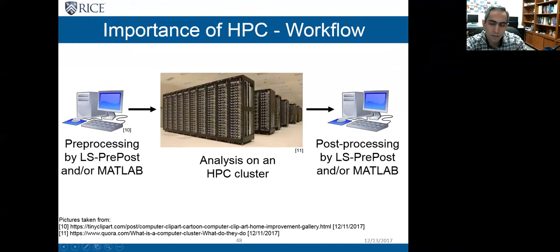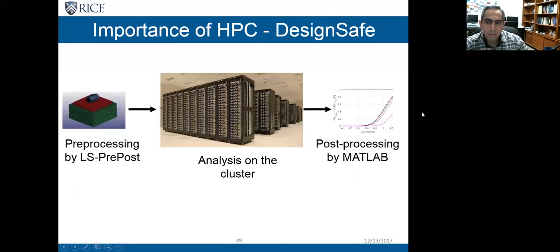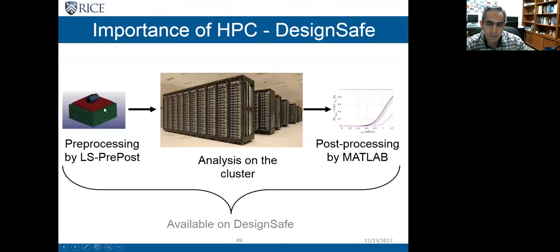The workflow that I usually follow to prepare my models and then analyze and post-process them is shown here. I usually prepare my models on my desktop computer, and then I submit them to a cluster, and then I transfer the results to my desktop computer again for post-processing. One cool thing about DesignSafe is that now this entire process is available on DesignSafe. Recently, a colleague of mine and I tested this process on DesignSafe. We created a finite element model in LS-DYNA on DesignSafe and then submitted that to Stampede. And then we did post-processing on the results.